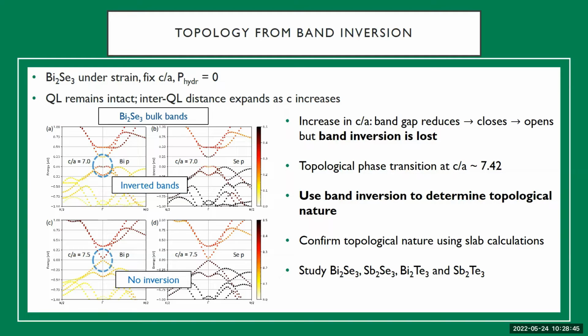structurally, the quintuple layer, which is that set of 5 atomic layers, remained almost intact, whereas the distance between them increased. And electronically, we found that the band gap in these materials decreased, and then it closed at some point, and then reopened, but the band inversion was lost. So if you recall, the band inversion is the important property which is responsible for the topological nature in these materials. So if the band inversion is lost, then the topological protection or the topological nature is lost. So it's a trivial material at that point.